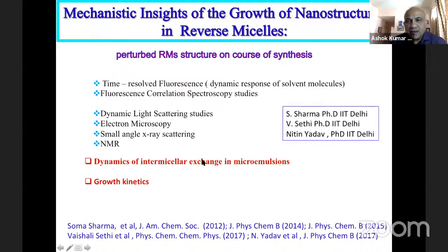So this kind of work, when you are making particles, you want to understand what is happening when the solutions are mixing at that time and how is the growth of the particle taking place. So that we can see that through time resolved fluorescence. We have done fluorescence correlation spectroscopy. One can use dynamic light scattering, electron microscopy, small angle X-ray scattering, NMR.